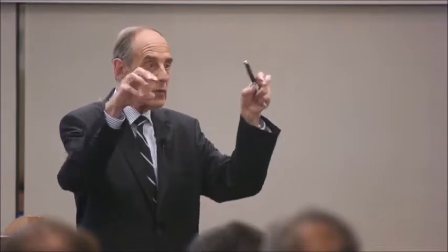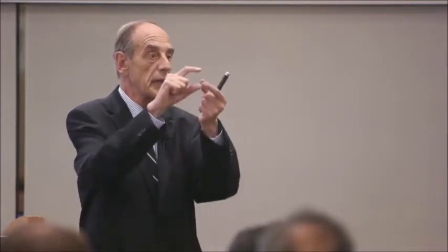Now we tried it with one ionic nanoglass, and this was silicon dioxide. We produced very tiny glass of silicon dioxide. And again, we get that answer. As soon as we join them up, we get a silicon dioxide structure which has a lower density and a different number of nearest neighbors. But again, we don't know where these nearest neighbors sit. At the moment, we are missing that.